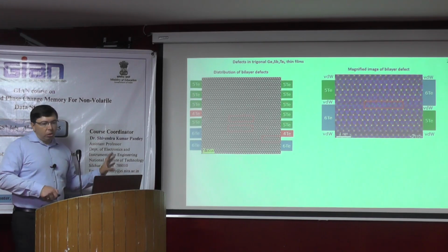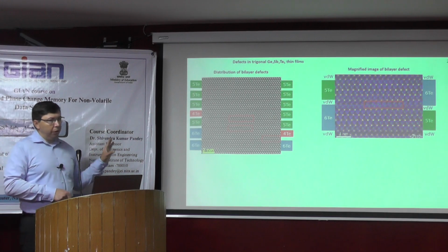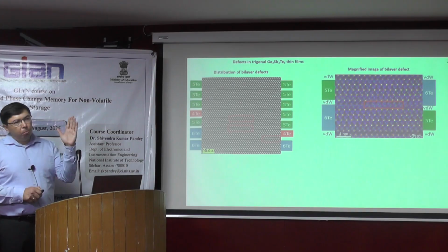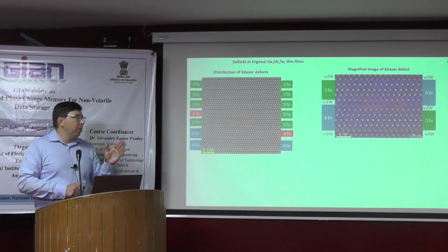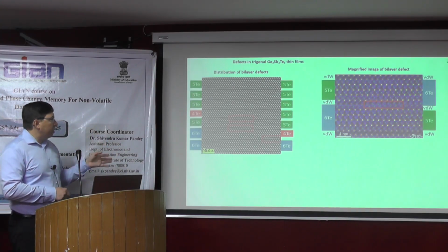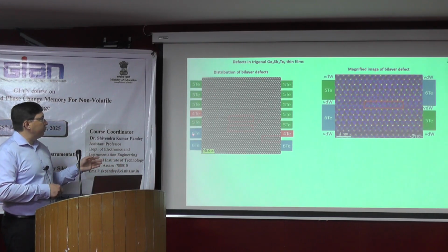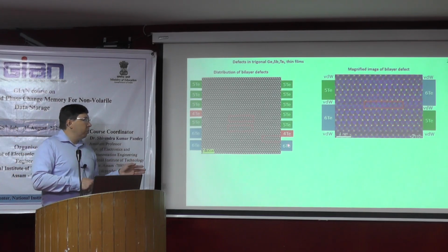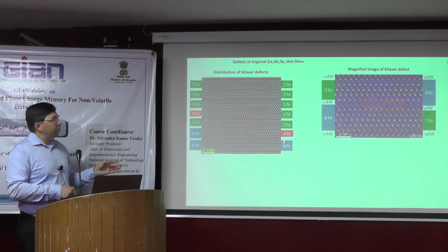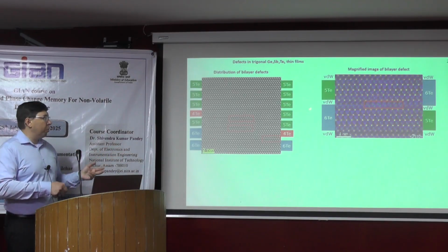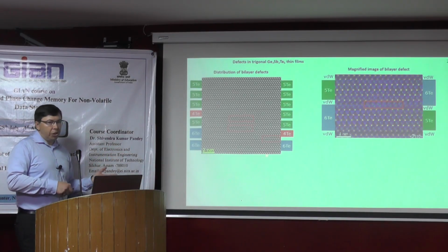This is also so-called chemical disorder in this system. In X-ray diffraction, you can see nicely that you produce GST225, but on the local scale, you see in the microstructure the formation of building blocks with 6 tellurium layers and with 4 tellurium layers. But if you combine them, 6 plus 4, on average you get 2 blocks with 5 tellurium layers. So this is a normal and intrinsic feature of this system.